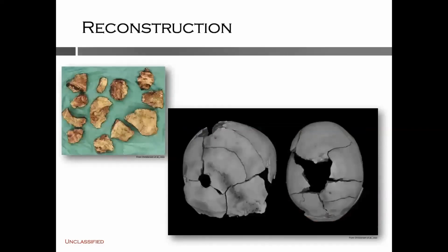And finally, reconstructing fractured bones can clarify branching and cracking patterns and can help understand the relationship between fragments. In this case, the cranial vault was received as 13 separate fragments, but there wasn't a clear picture of the fracture event. After reconstruction, however, a cone crack, radial cracks, and circumferential cracks all became quite apparent.